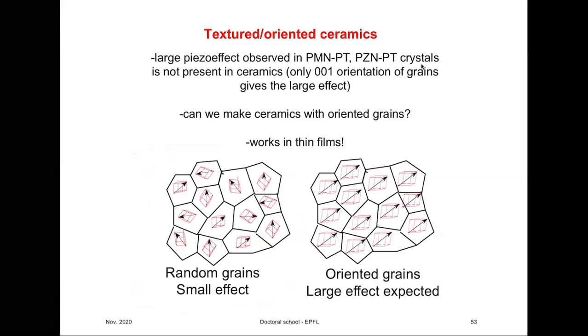But the response will be relatively small with respect to that in the crystals. However, if we can orient all grains to be in the same direction, and for PMN-PT, it should not be the direction of polarization, but under an angle of about 50 degrees with respect to polarization. So they are all oriented in this direction.